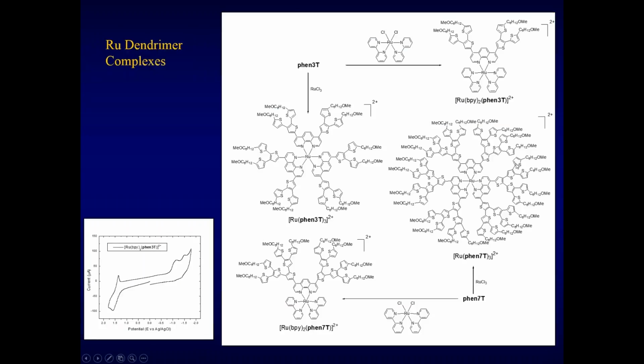On the other hand, in cases where we have utilized selective solvents, they actually pack in columnar phases to form this type of nanowires. So here you can see that AFM offers a direct visualization of the supramolecular assembly of these dendrimers to form these structures on flat surfaces such as mica or graphite. We have since then prepared different types of polythiophene dendrimers with different core groups.